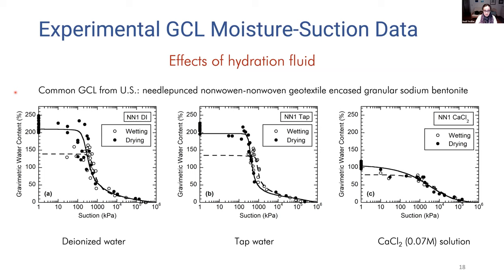In this case, we're looking at this GCL material tested when it's exposed to three different solutions: deionized water, tap water, and a 0.07 molar calcium chloride solution. This solution represents moderate to harsh leachates that we expect to encounter in landfill environments. We see that for the deionized water and tap water tests, the response of the GCL is similar. We have distinctly different wetting and drying curves. The drying curve is up here, the wetting curve is down here. The two curves are getting closer as suction increases. When we switch to the calcium chloride solution, we notice a big difference in the response of the material.